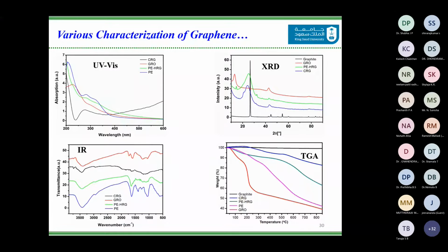Further, if you observe the XRD spectrum, the XRD peak of pristine graphene, or you can call it graphite, appears at 26.4 2 theta. However, during the course of oxidation, various oxygen functional groups enter between the spaces, leading to a shift. You will see a disappearance of this pristine graphene peak, and you will see a diffraction at 2 theta 10.9.